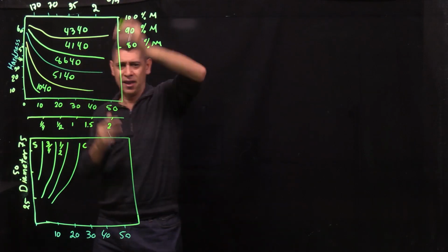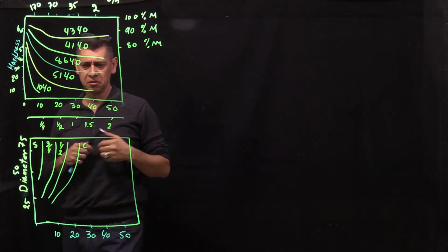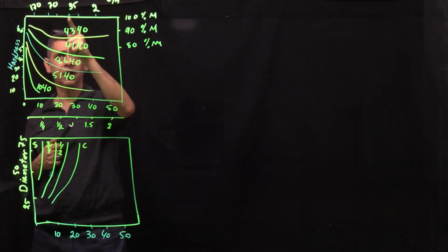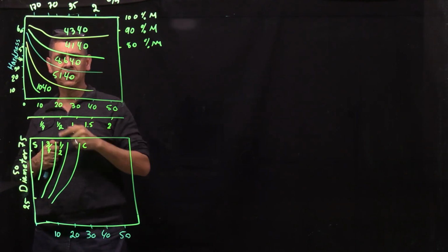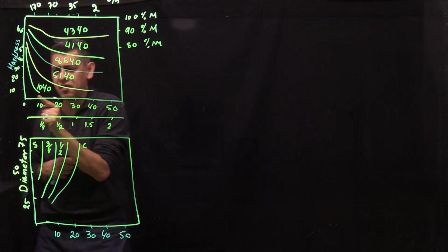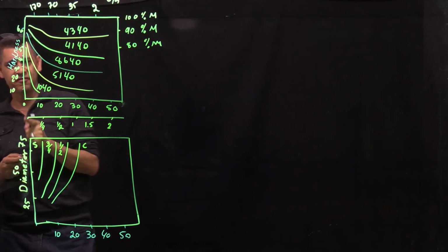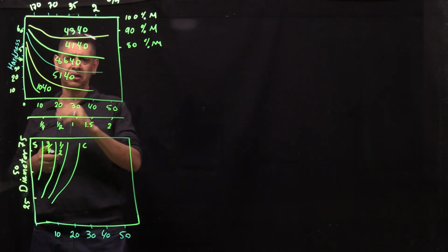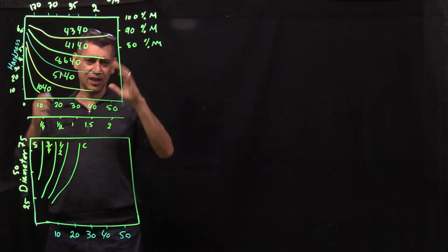The other way, if you have 10 of them and you want to compare them, you pick a cooling rate, either from here or from here, and then you compare the hardness. Don't pick a very fast cooling rate, because with a very fast cooling rate, none of them may get martensite. You pick a relatively slightly slower cooling rate. That's one way.